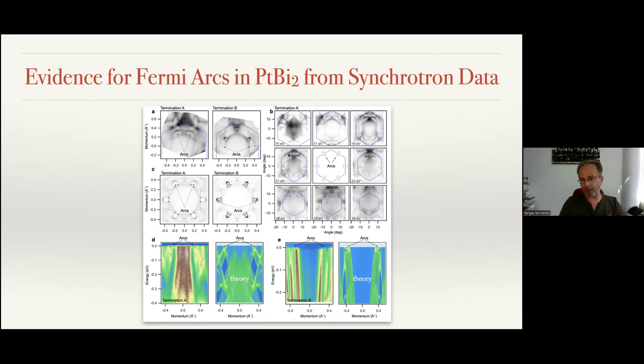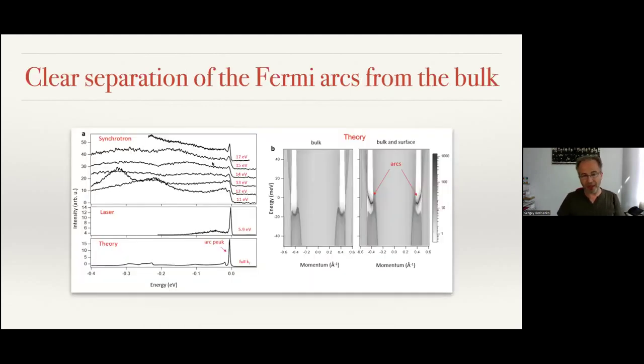different k_z. If we study surface states, they should not depend on the photon energy. Of course, the intensity could be a function of the photon energy, but generally they do not depend on photon energy. So this was a confirmation that these are surface states. Again, we did it at different energies and with the laser, compared with the theory, so there was no doubt that these are exactly these states, and they are very well separated from the bulk.